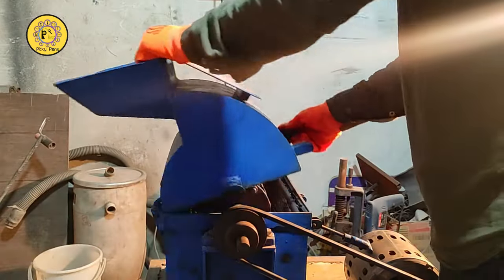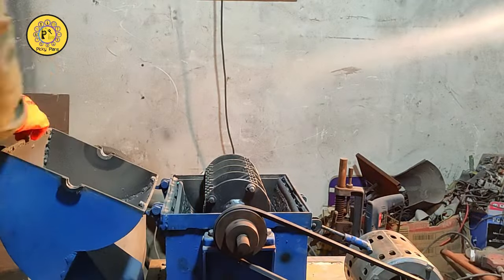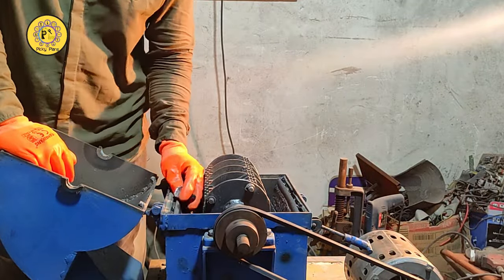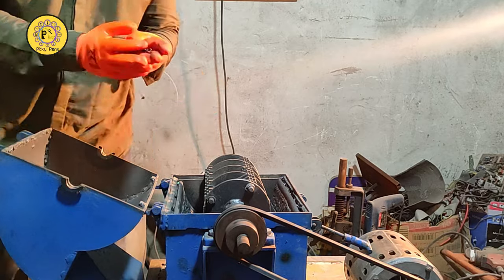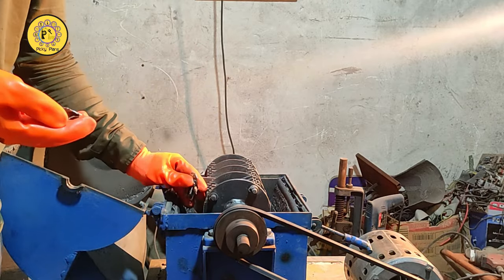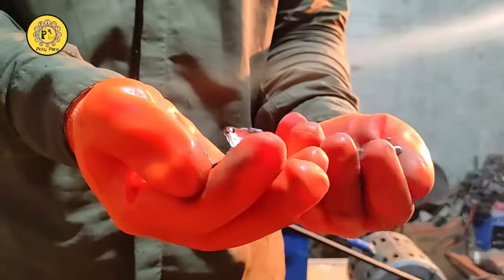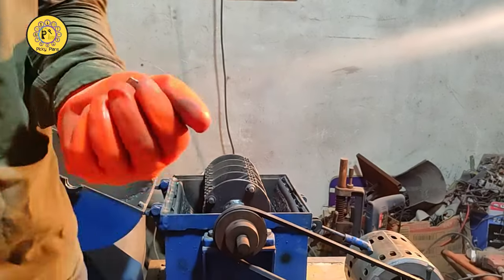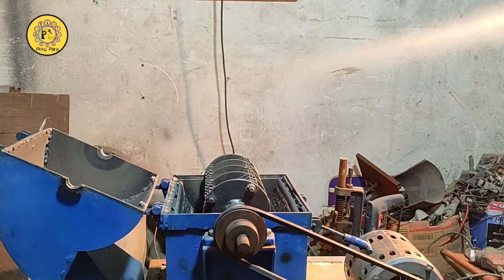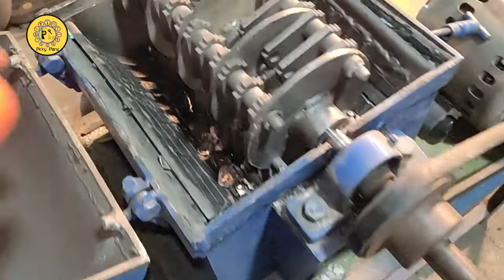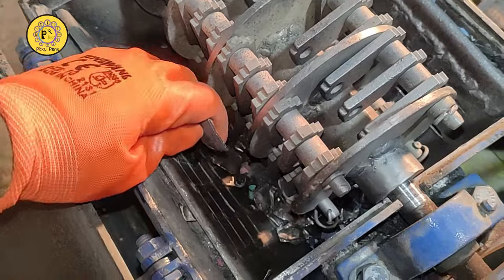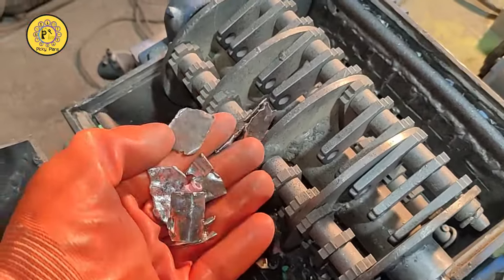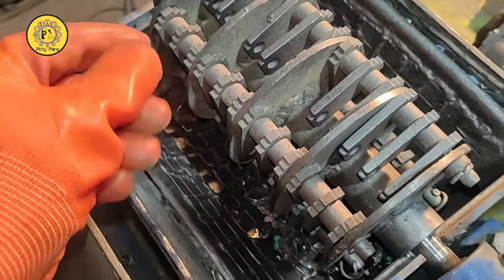I opened up the hammer mill to see what's going on inside, and I saw something interesting. The pins fell out of the tray and the steel parts remain in the tray. That's a good result. But there is an issue with that. After accumulating enough steel inside the hammer mill, it's gonna get jammed, and to prevent that I need to evacuate it from time to time.